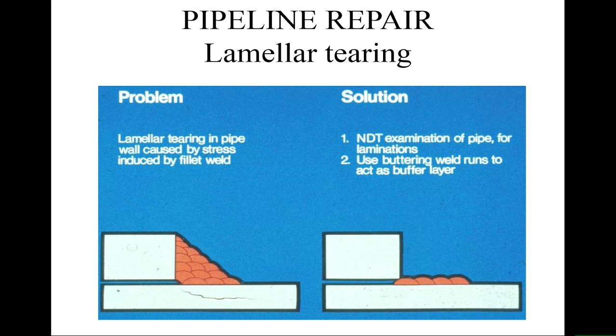And then what you also do is deposit some weld metal onto the surface without it contacting the part you're trying to join to, and then allow that to cool, and then you can weld on top of these what we call buttering runs. These are runs that are done to prepare the surface for connection to the other parts.